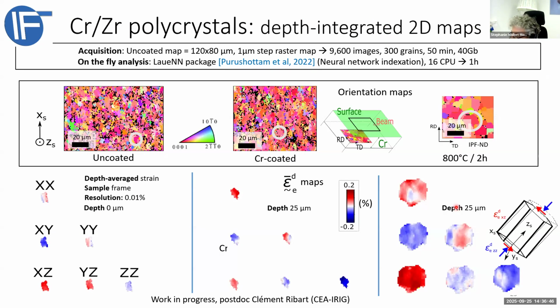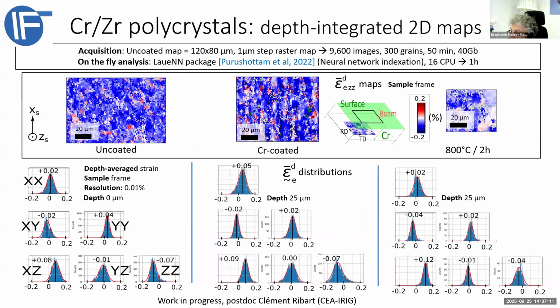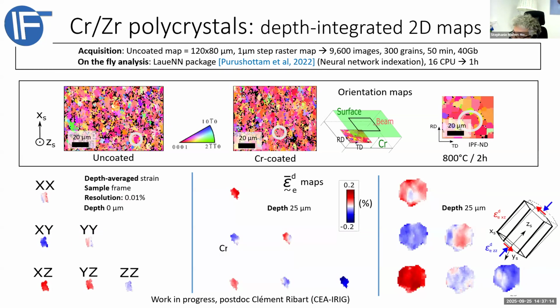Okay, and the last example is on the polycrystal, chromium that covers the zirconium polycrystal. So you can do these orientation maps as you could do with EBSD, but with the X-ray, with a very high resolution, you can have the strain in any region of your sample. But also, let's go back there, you can select one grain and see how the strain is changing inside the grain. So this is a beautiful example.